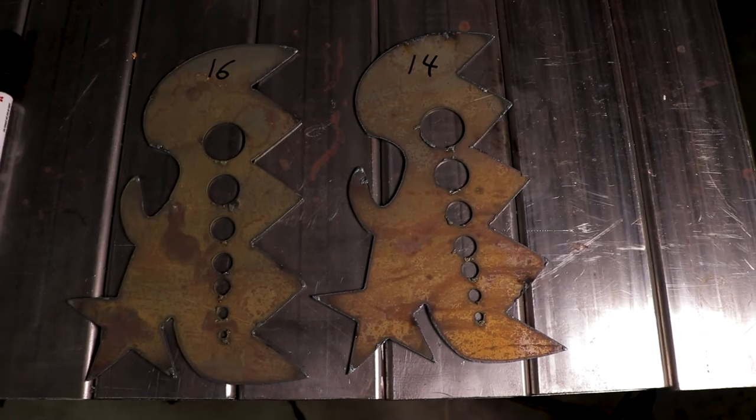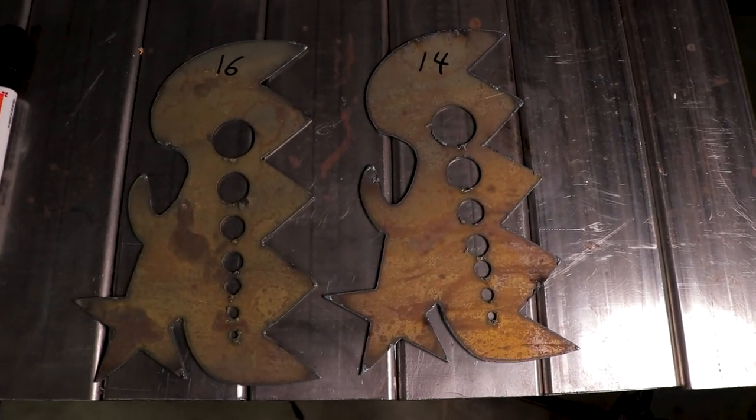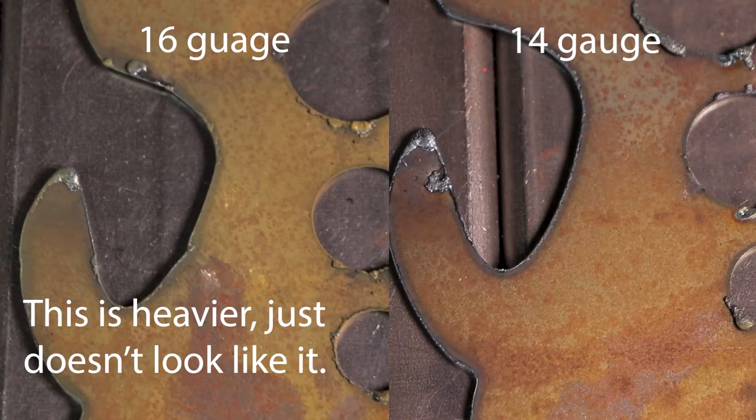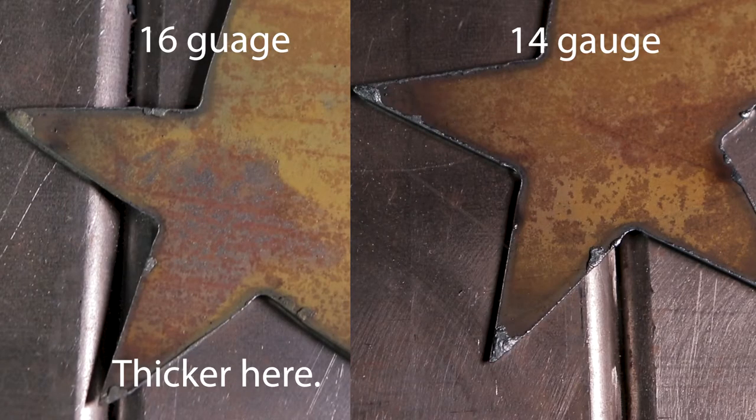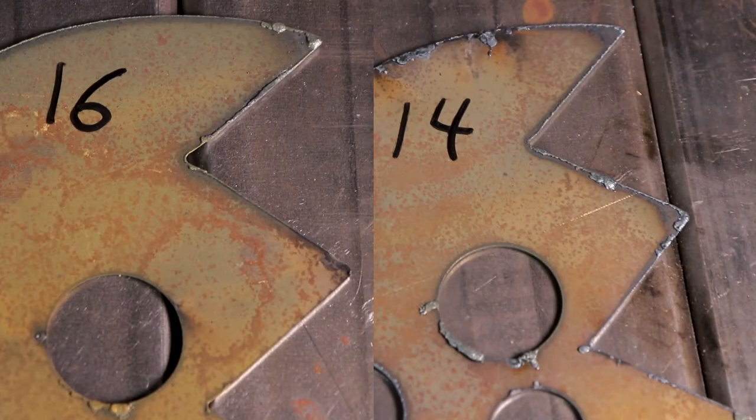On the back it's a little bit of a different story. If you look at the 16 gauge sample it had more low speed dross, actually a fair amount more and boy was it thick. And this is really where my problems come from. I cut this stuff out, I want to get it prepped for powder coat or get it sealed or do whatever treatment I want to do on it, and I cannot get this low speed dross off. So if you have any ideas about how I might be able to mitigate this or keep that from happening, I'm all ears.